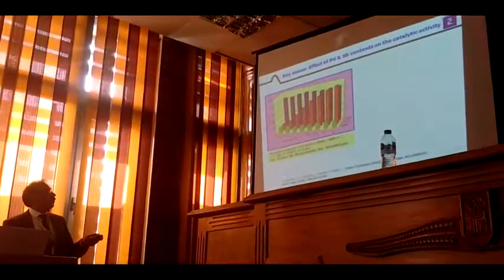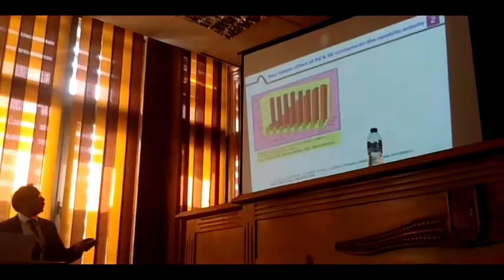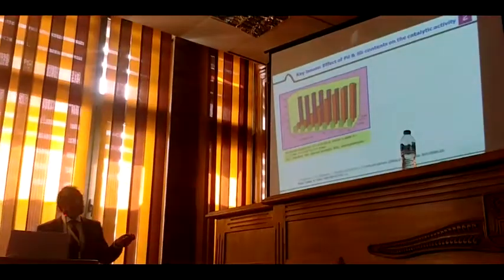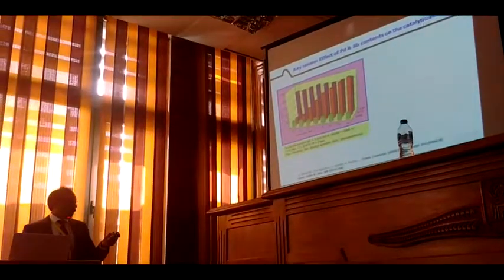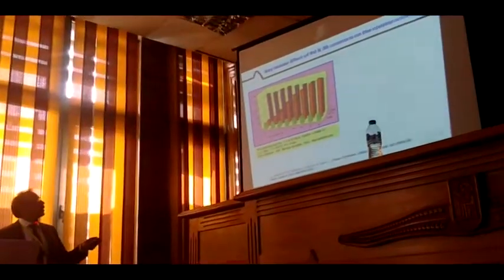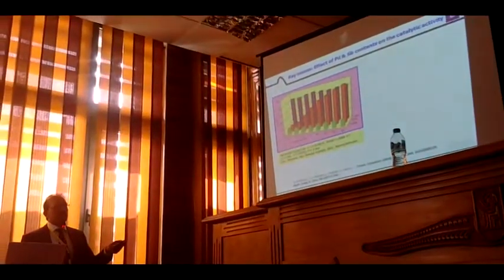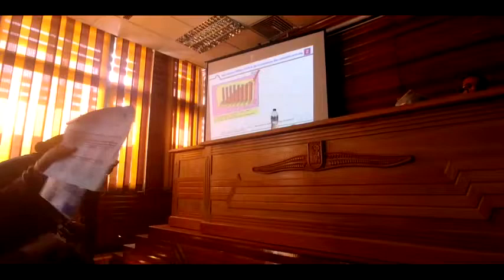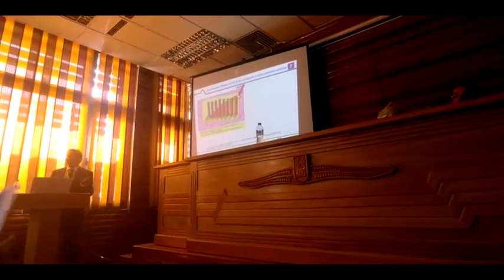So this is the effect of palladium loading, 0.5 to 20%, on the conversion, activity and selectivity. If you look at this, the conversion is increasing rapidly up to 10% and then increasing slowly beyond 10%. So in fact, 20% palladium is the best one, and the selectivity is independent of conversion. This means the benzyl acetate is quite stable product. It is not undergoing any further reactions, consecutive reactions.